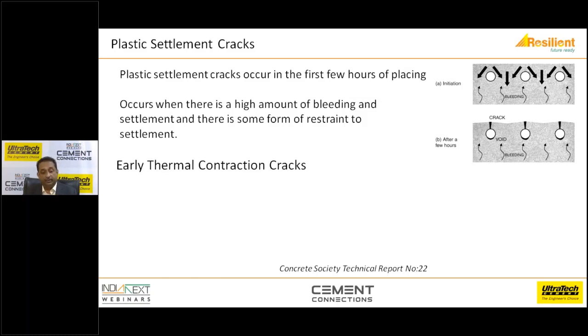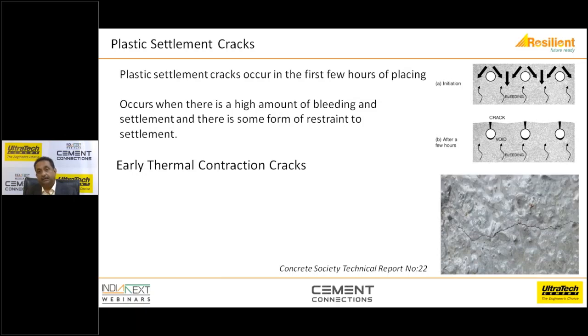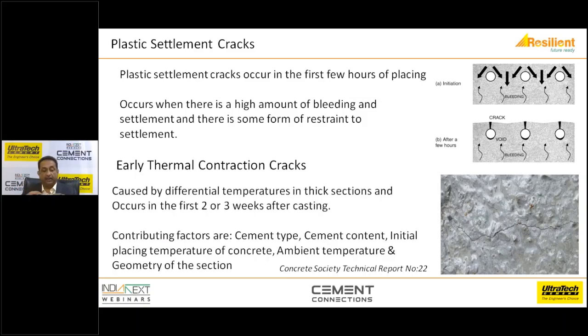Another crack which is normally observed in deep sections or foundations are the thermal cracks or thermal contraction cracks. This is the typical way in which the concrete cracks. This happens in thick sections, where the differential in temperature and the temperature gradient actually is the cause of this problem.